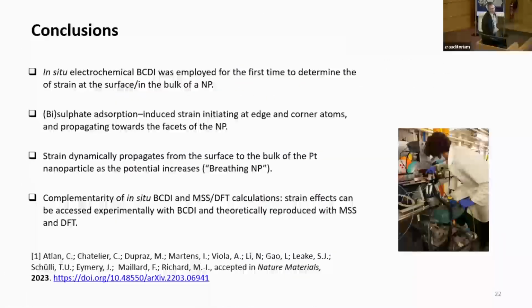And that brings me to the conclusion. So for the first time, we made in situ electrochemical BCDI. We investigated the adsorption of anions. This is one of the very simple processes in electrocatalysis. It was impossible to enter the surface oxide region, nor the hydrogen adsorption region, but we are progressing continuously. So I think many things will emerge.